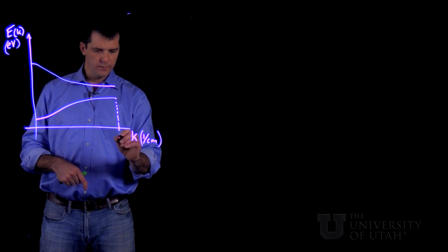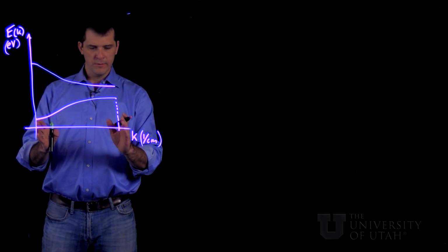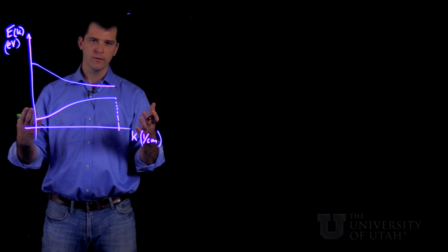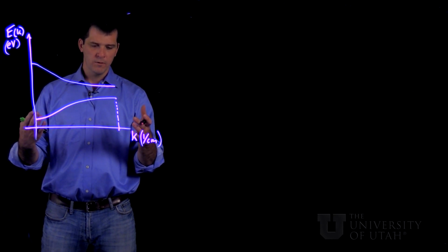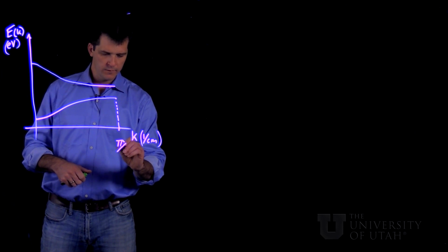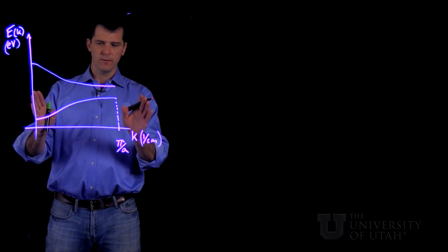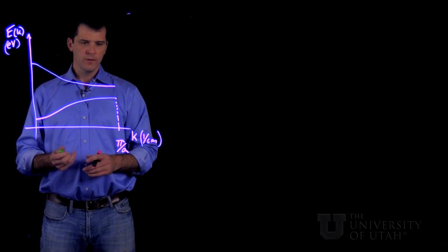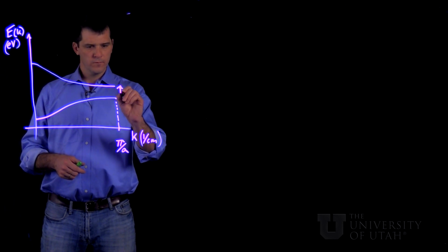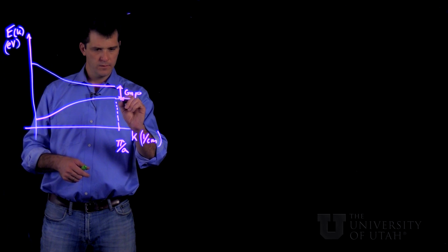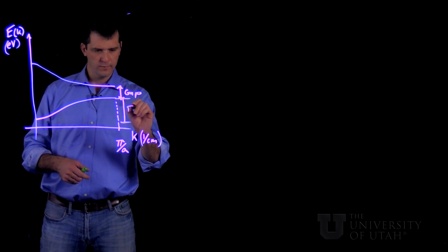So there's a limit to how far out in k the solutions can go. Because we were working with a cosine function, it turns out that solutions can only exist between plus and minus pi over a. And I'm only drawing half of that right here. So here's our band gap, and here's our band of solutions.